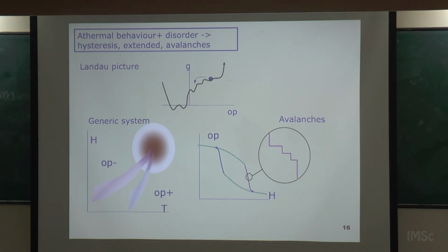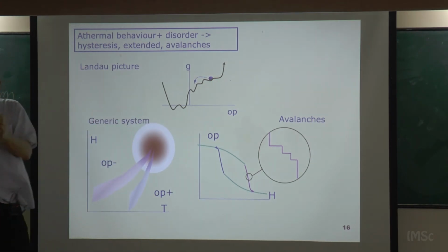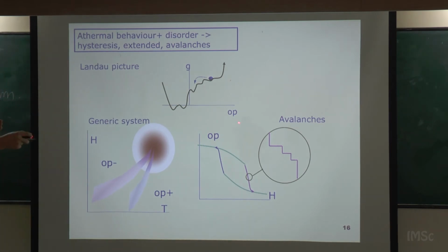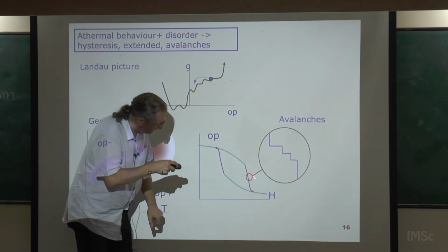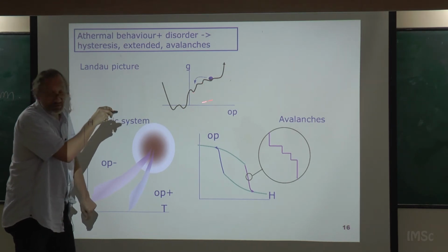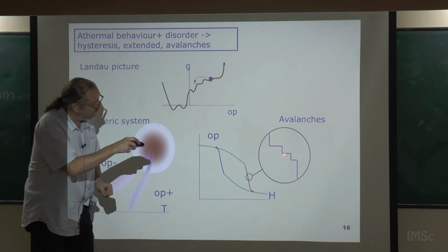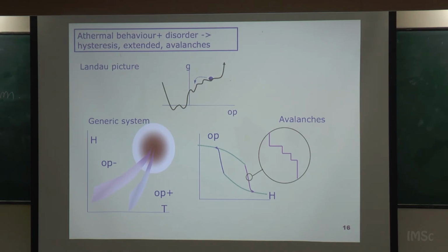If you have disorder and you have athermal conditions, then you are tilting that, you are driving, so you are tilting this, and the system jumps every time the local minimum disappears, and then goes to the next one, and then to the next one, and then to the next one. But you have to drive it until you change the magnetization from positive to negative or vice versa. And this explains why the two lines are in fact regions. The transition starts here and ends here, and when you go up, it starts here and ends there. Okay? And this explains also why in these curved regions, when you magnify and look at what's happening, you discover these steps, because these steps correspond to the jumps from one well to the other. And if there is a barrier, you tilt and nothing happens, nothing happens, nothing happens, and then suddenly, clack, something relaxes. You go to the next well, and you get this kind of behavior. So that is one of the possible scenarios for explaining avalanches, okay?